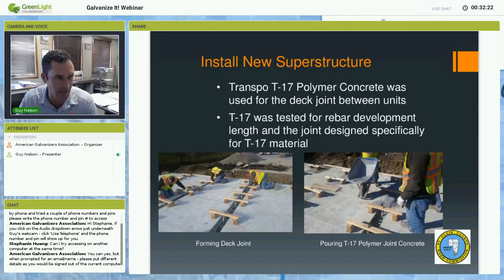Their polymer concrete achieves a strength of about 9,000 psi. The nice thing is that UHPC sometimes takes a little longer to set up, whereas with the polymer concrete, within 4 hours you're achieving strengths over 6,000 psi. So it's very fast setting, and the next day you can basically bring out traffic and continue with your construction work.